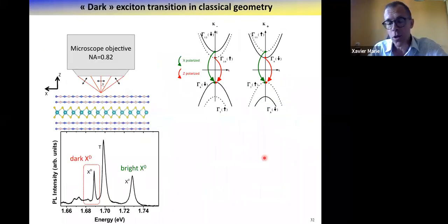In fact, as you know, if you look at the literature, very quickly we realized that you don't have to do this complicated experiment to evidence the dark exciton. You just have to use, as most of us do in optical spectroscopy, a high numerical aperture objective, because the flakes are usually small, we do small spots, so we use high numerical aperture objectives. And because of that, you can collect with this high NA objective both in-plane light, which is polarized in the plane, and also the Z component.